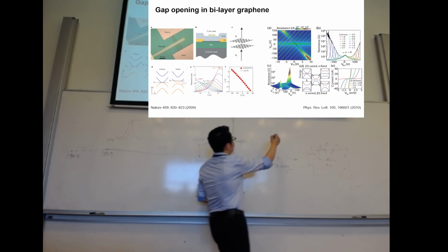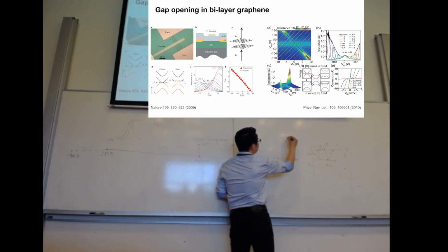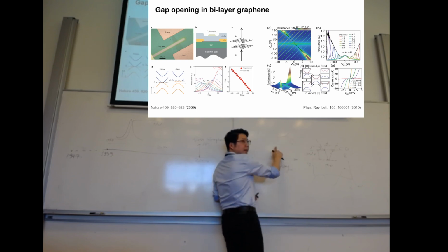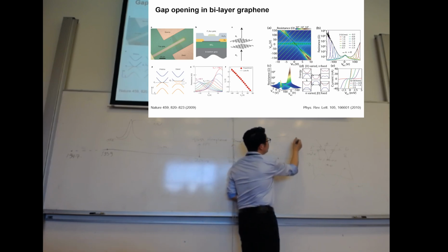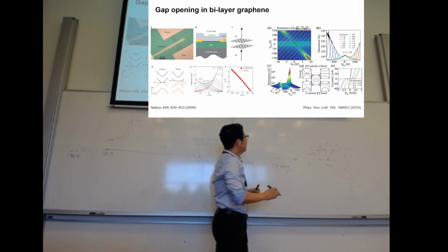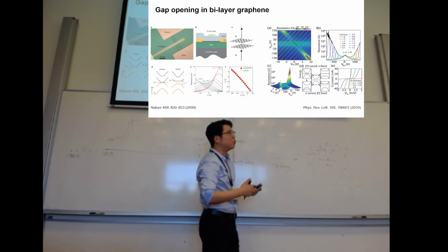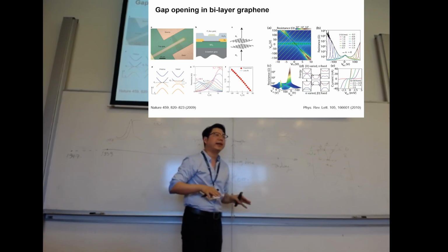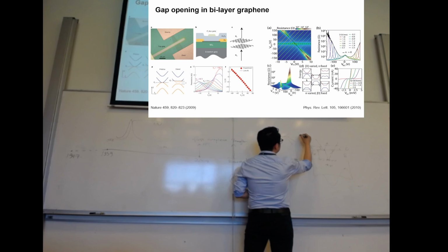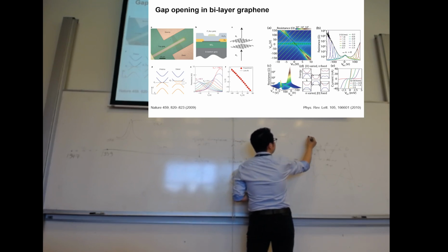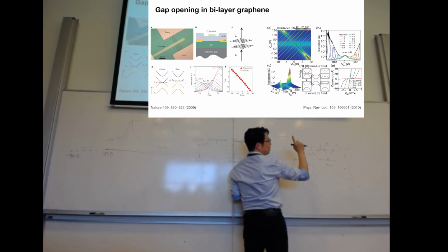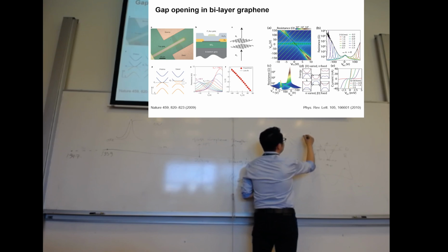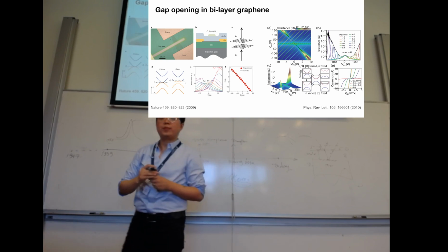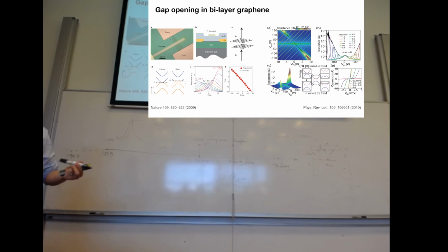So basically, let's forget about the other bands. There are just the two bands. For neutral bilayer graphene, they're touching each other at one point. If you apply a voltage, which turns out to be an electrical field vertical to the plane of bilayer graphene, you pull down this band somewhere a little bit here, and you pull the other band a little bit up. So this kind of band inversion, not strictly inversion, crossing, will create some kind of hybridization of the two bands, and opens a little gap like that. So this is well known theoretically and experimentally, and this gap is proportional to the vertical electrical field.